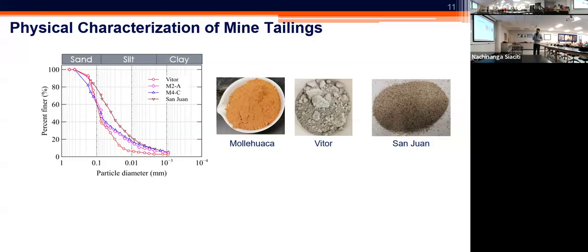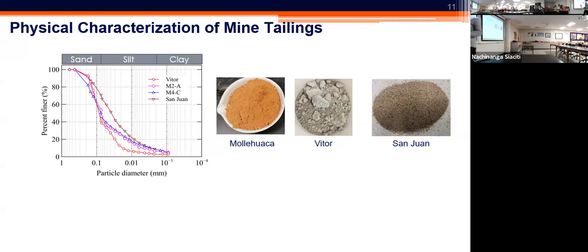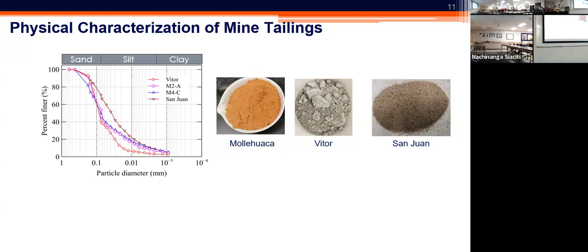So that essentially tells us out of the entire assembly of the grains, how much of it is considered as technically the fines, that is the kind of combination of the silt and clay, and how much of it is potentially sand and even larger type of grains. So when you look at the gradation evaluation for these samples, you can realize that these have somewhere like 40 to 60% passing of the sieve number 200.